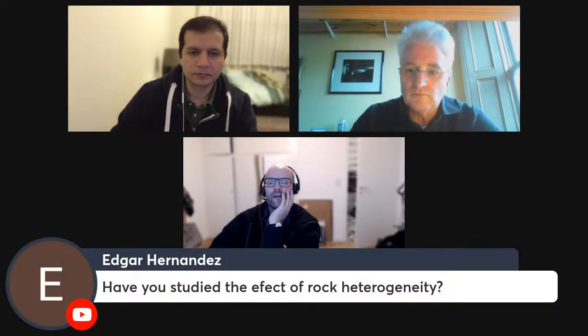Edgar Hernandez is asking if you have studied the effect of rock heterogeneity, which links a bit with a question I would have: are there plans for further measurements? Yes, we'll be developing proposals to extend this. We did look at rock heterogeneity with the granite tests because we had a pristine intact sample, and then we put some cracks in it, deliberately putting in heterogeneity. And we saw significant differences, like I showed. Not least the fact that heterogeneity tends to make the crack growth smoother. So all of your statistics are smoother. It's an odd thing, but once you put in disorder, it makes the evolution of the number of acoustic emissions per second, or the damage per second, much smoother.